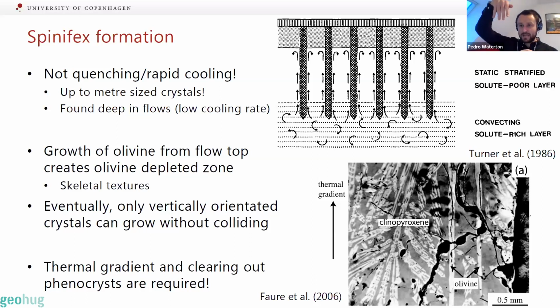As these crystals grow down into a more olivine-rich liquid underneath, eventually only the ones that are vertically orientated can continue to grow without colliding with the other crystals. And so we get this platy spinifex where everything is aligned deeper in the flow. It's really important to note that this only happens if there's a thermal gradient, and there's some really nice experiments by Faure et al. 2006 that show this. And you also need to clear out the phenocrysts from the lava first, because if you have any olivine phenocrysts there, then the olivine will just grow on top rather than forming these long skeletal spinifex.